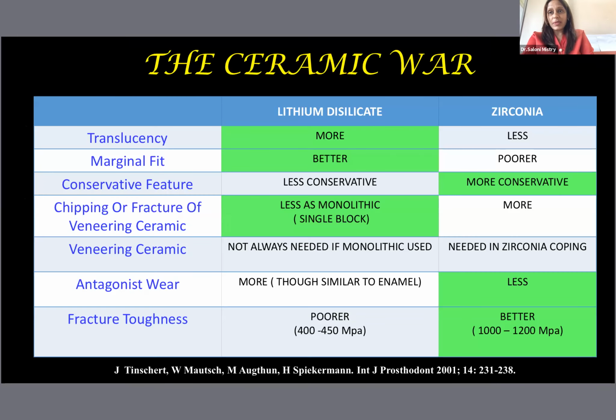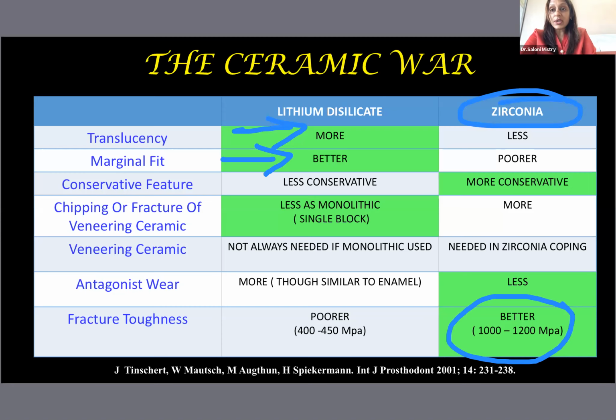So now we come back to the ceramic war. If we taper down to two basic ceramics that we are talking about in rehabilitation zones, we understand that lithium disilicate is obviously the more translucent. It has a better marginal fit, but zirconia obviously is better in strength, 1000 to 1200 megapascals. So again we come back to aesthetics versus weaker and stronger tooth. In full mouth rehabilitation cases, zirconia is going to be our ceramic of choice. Sometimes if you have to use veneering, then in copings, you can veneer the ceramics with the help of lithium disilicate.